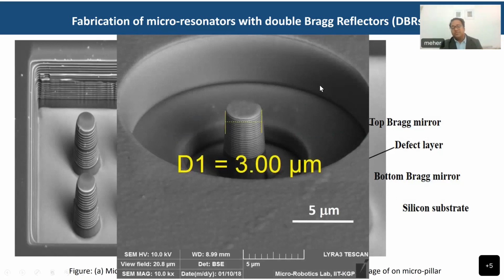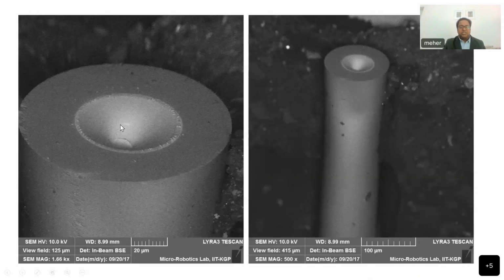Then we used focused ion beam to make these kinds of patterns, which are around 3 microns, very challenging structures. These can be integrated on the tip of an optical fiber also, and again can be used for remote location sensing and other applications. Here also is a concave structure we tried to make on the tip of an optical fiber. This is again very small in area, a multi-mode glass fiber. In this case, the focused ion beam etches the material in a certain geometry.